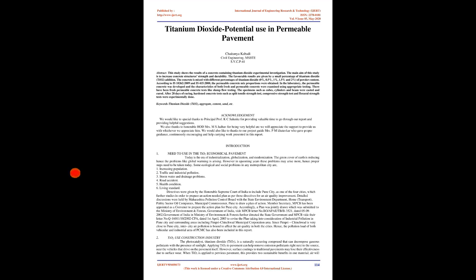In the laboratory, the permeable concrete was developed and the characteristics of both fresh and hardened concrete were examined using appropriate testing. There were fresh permeable concrete tests like slump flow testing. The specimens such as cubes, cylinders and beams were cast and cured. After 28 days of curing, hardened concrete tests such as split tensile strength test, compressive strength test and flexural strength tests were experimentally done. Keywords: titanium dioxide, TiO2, aggregate, cement, sand, etc.